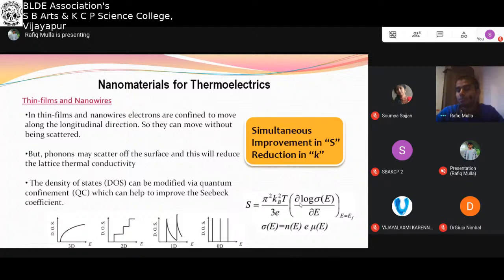So it is a derivative with respect to energy. If there is a much larger change, then this value will be more. So that's why the Seebeck coefficient will be more. But in case of bulk, it is a smooth change, so not much change. If you consider here, it is just flat, so it is constant, almost a very negligible change. So whenever we have a derivative term, if the change is much in the parameter, then we get a large value from that term. So Seebeck coefficients can be effectively improved by decreasing the dimension from bulk to thin films and nanowires.